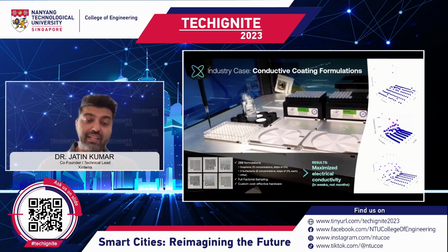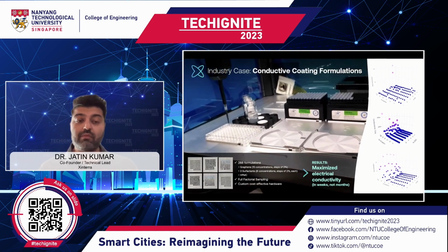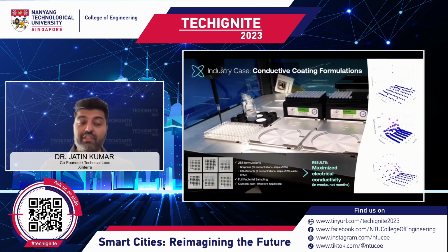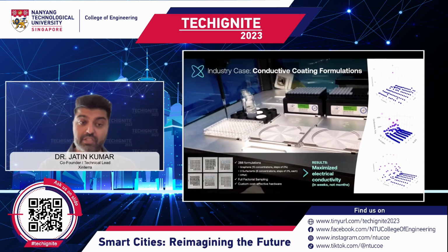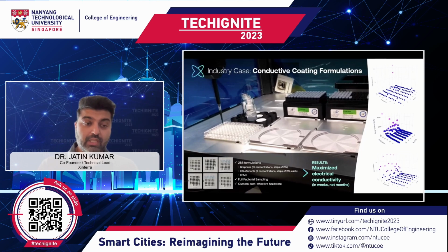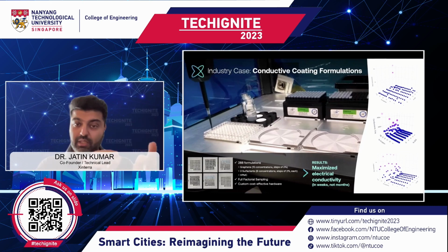There was graphene, surfactant, and hydroxypropyl methylcellulose, which is a film-forming polymer, a sustainable polymer. And the target by the company that we're partnered with here was to understand the relationship between different surfactants and graphene towards achieving conductive films. And so what you see here was a formulation. Each well plate which is being pipetted into is a unique formulation completely. A different ratio of graphene to surfactant, a different type of surfactant, or different ratio of surfactant, and a different amount of film-forming polymer. This pipette is touching the tips to reduce droplets and to increase accuracy.